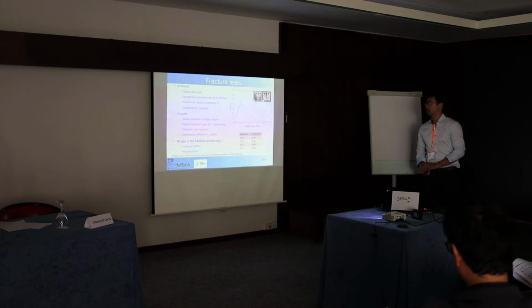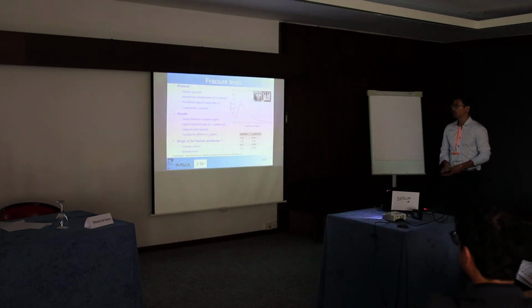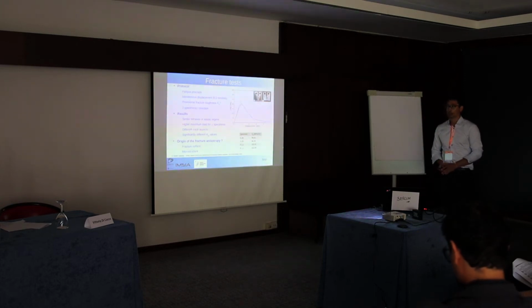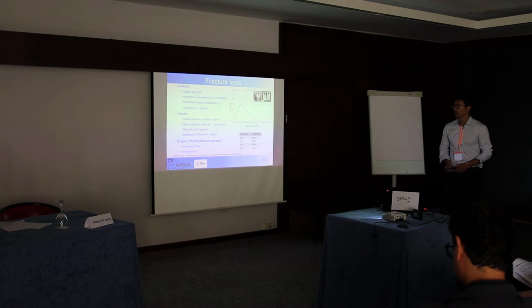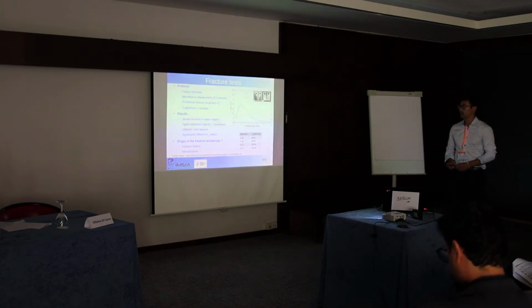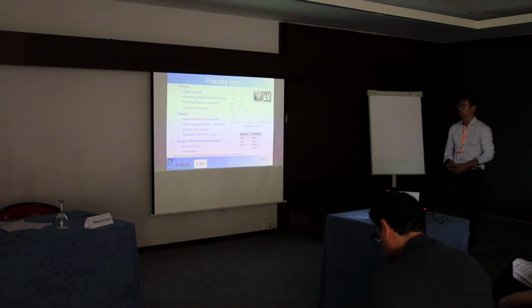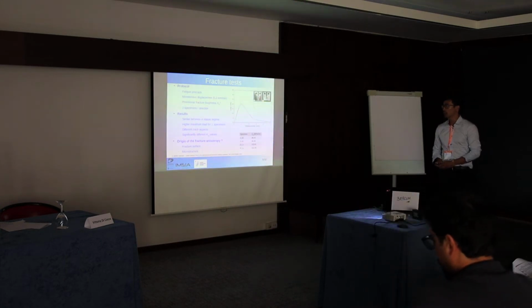Next, the specimens are tested in a very classical manner. First of all, they are preconditioned in fatigue to create an initial pre-crack, and then a displacement is applied in a quasi-static fashion. The load and the displacement are recorded during the test, which allows to compute a provisional fracture toughness value that we call KQ.